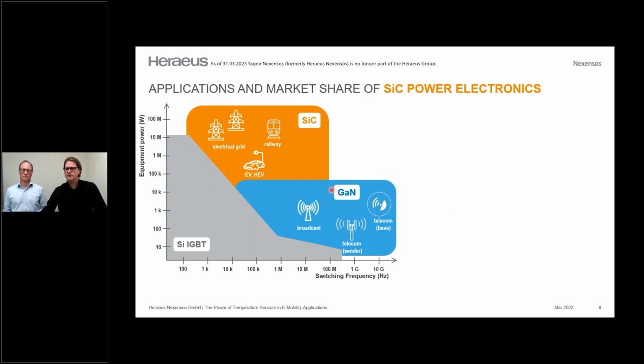Both of these technologies are key for the future trends. That means if it comes to higher transformation of power, you need silicon carbide. If it comes to higher frequencies for switching, it comes to gallium nitride. One is more or less for the automotive world, the other is more for the telecommunication market, but both lead in the end to higher temperatures, which is then optimized and controlled with the sensor from Heraeus with a PT element.